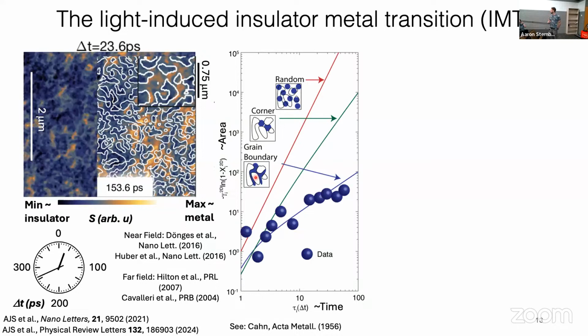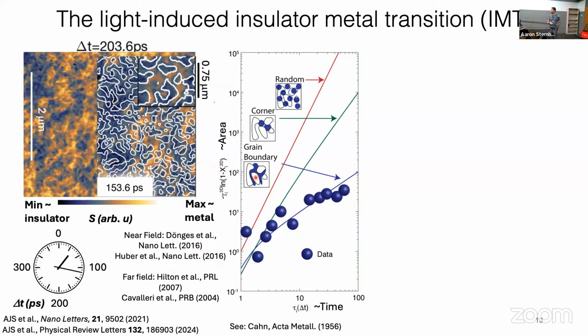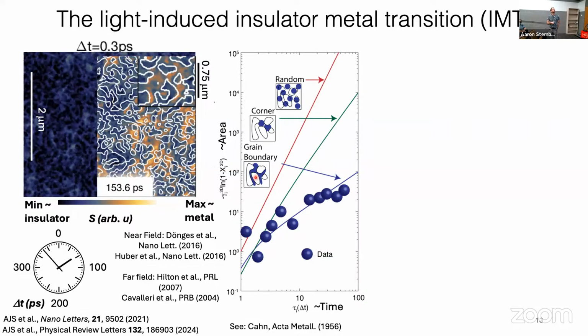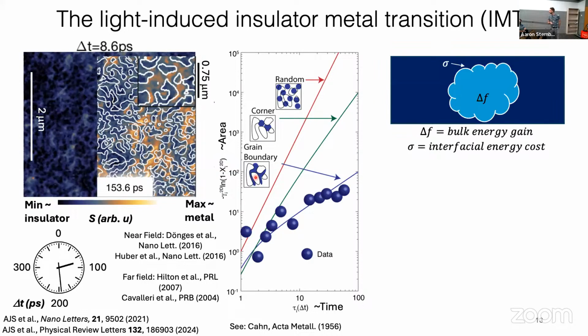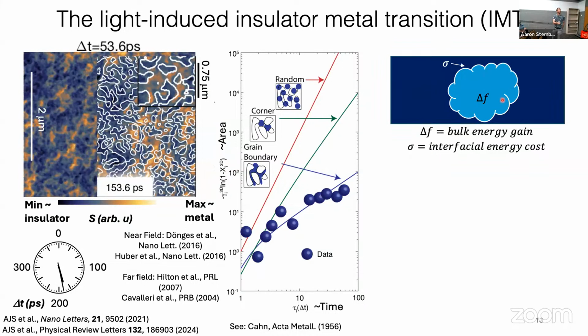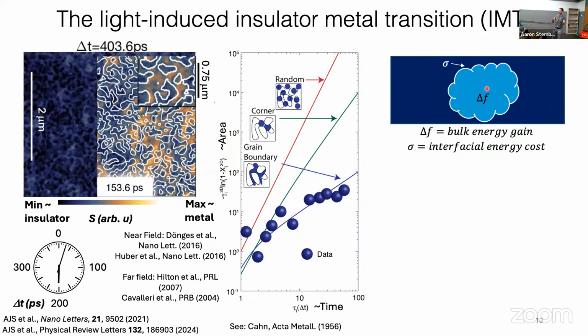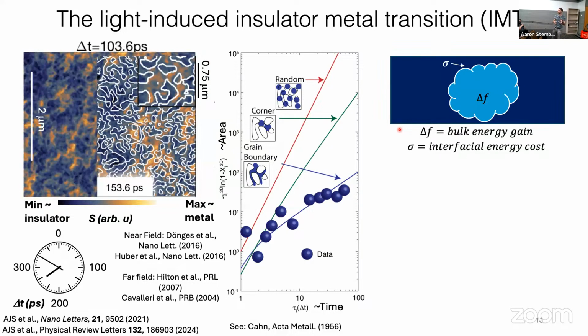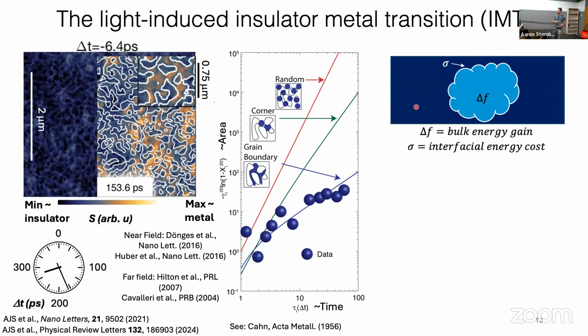So it appears that some type of boundaries, twin domain boundaries, grain boundaries, are anchoring nucleation sites in our film and causing the transition to be inhomogeneous. All of that is pretty much what you would expect just from basic classical nucleation theory, where you can take a domain that emerges and it may have some irregular shape, but in the interior of the domain, you gain bulk energy by moving into a new metallic phase. However, this comes with an interfacial energy cost. In order to form an insulator-metal interface, you have to pay the cost of creating this interface.